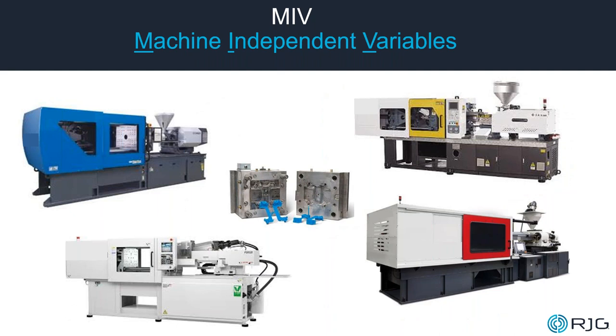The second type of variable that can be documented for a given part process is called MIV, or machine independent variables. This defines a specific molding process from a plastics point of view. This process can then be transferred to other pre-qualified or capable machines within a short period of time. Mold temperature mapping, using the temperature measuring instruments that we talked about earlier, is very much encouraged during this stage. With the mold temperature mapping completed, and later if the mold started making parts that no longer meet print specification, you can then verify if the mold temperature is playing a role in this issue.